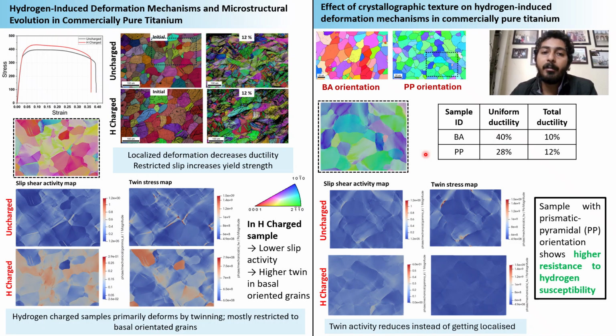What will happen if we remove all this red color grain? Will the hydrogen embrittlement resistance increase or decrease? On testing the second orientation, we found that in this second orientation the hydrogen embrittlement resistance increases, as the uniform ductility reduces by 28% rather than the 40% in the previous case. And all this hypothesis was supported by crystal plasticity simulations.